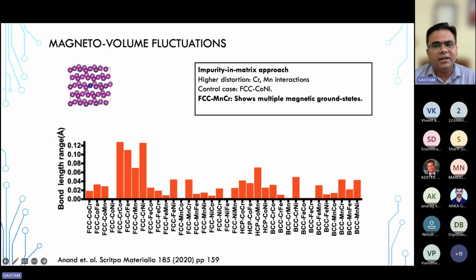One thing which was very clear is that cobalt and nickel show very negligible atomic scale distortion, but chromium in FCC form showed significant distortion. Another interesting case was manganese. Manganese was showing a range of different distortions. In some cases it was showing distortion, in some cases it was not.